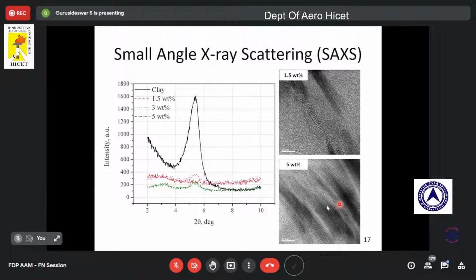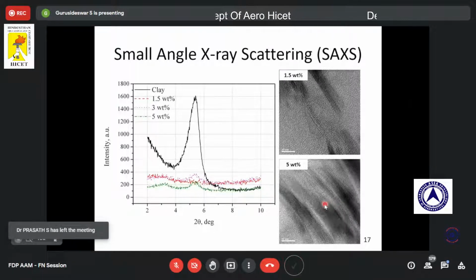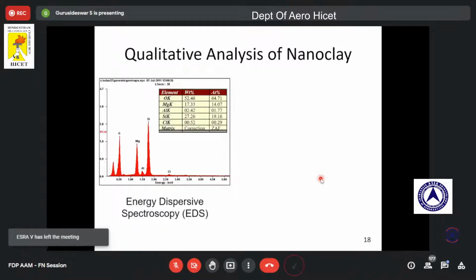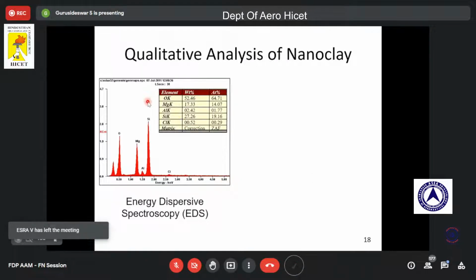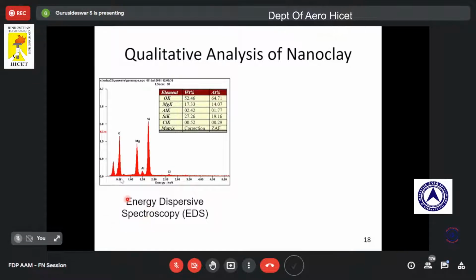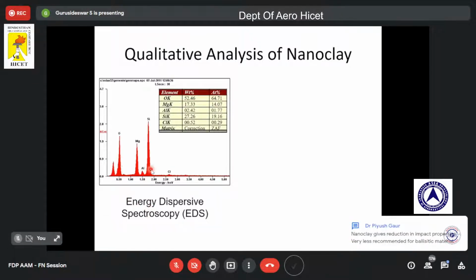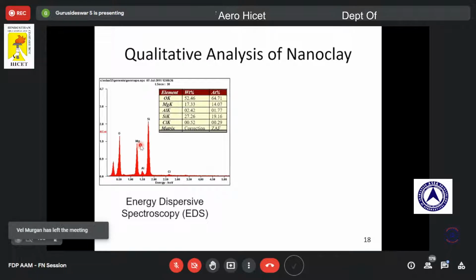So we have understood the dispersion of clay using different techniques: from wide angle X-ray scattering, from small angle X-ray scattering, and also from TEM, transmission electron microscopy. Then we wanted to understand the composition of nano clay. So this is EDX, which has been coupled with scanning electron microscopy. This is energy dispersive spectroscopy. You can see the clay has silica, alumina, and magnesium. So these are the major composition of clay, which we all know.